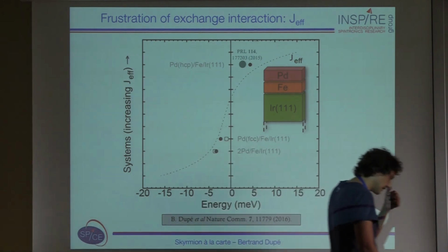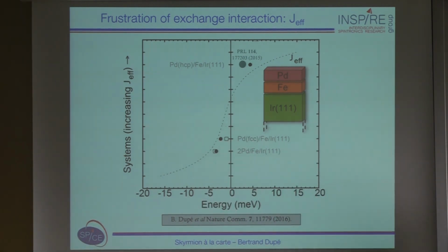So we decided now to classify the systems as a function of J effective, to see where we could find frustration. And so here is the palladium HCP, iron on iridium 111, and the J effective is very close to the one obtained from experiments. And you have these two other systems, palladium FCC, iron on iridium 111, and palladium, iron, iridium 111, which have a negative J effective.